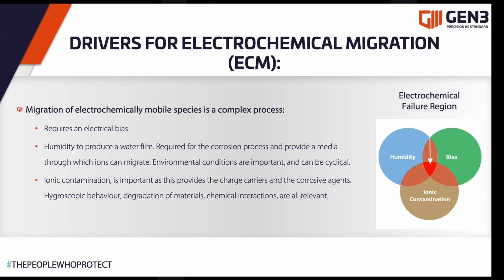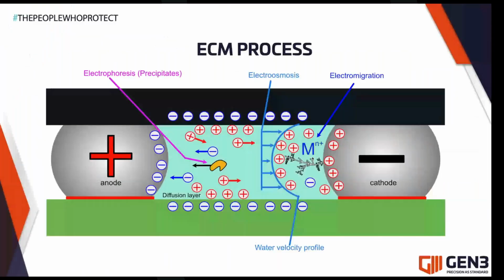Next slide. So here's a schematic, perhaps, of what could be a BGA. So we have an anode and a cathode, and we have filled up the space between the component and the board with a moisture layer, which is now quite thick, obviously, with the size of the solder balls. But in SIR on open combs or other parts of circuit boards, we'll have a very much thinner water layer, perhaps less than 100 nanometers. And hence these pathways can become quite tortuous and not, as you can see here, which you have presumably a relatively easy flow for the ions.